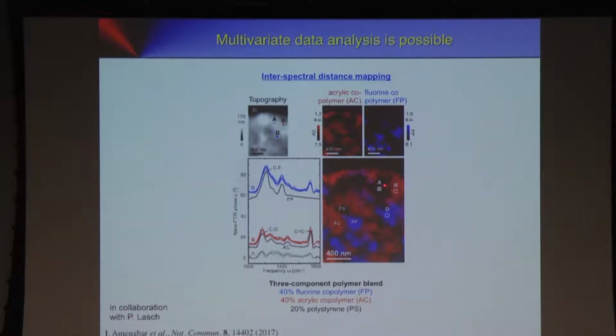So actually, we could identify here these purple areas, and this is rather interesting. In these purple areas, we couldn't get any agreement to any of the initial components, not even by making a linear superposition. And talking to chemists, this could be indicative of chemical interaction at the interface between the polymers, giving rise to bond shifts that cannot be explained by just a superposition of the spectra. I don't have time to talk about that. So this could be also very interesting to study chemical interaction at interfaces of polymers and any other material, with nanoscale precision, of course.